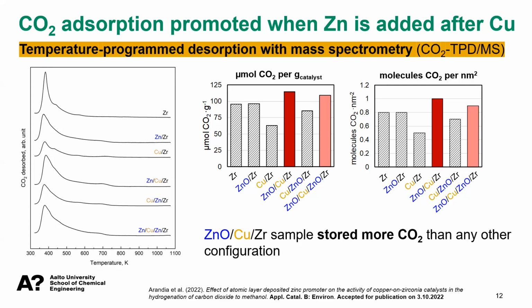In any case, what I want to show you is that we observed that when the zinc oxide copper zirconia sample stored more CO2 than any other configuration. So you see the results, we see differences. So the order in which the metals are added to the system matters a lot. And we see that the CO2 adsorption is promoted when the zinc is added after, because this was the second catalyst with the highest CO2 adsorption capacity. So we observed differences,